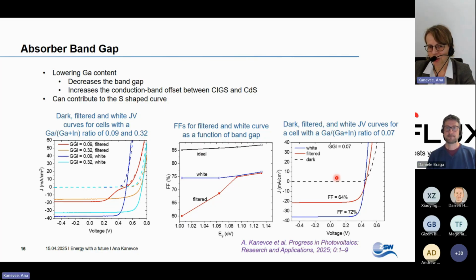So in a single junction, this is why we encounter those problems, because if you optimize a cell for a single junction, it's completely relevant to say, I need to expose my cell for a couple of seconds to white light and it's working wonderfully. So I don't think that this is... There was quite a bit of research on this S-shaped curve some years ago, but this was mainly from academic curiosity, because we wanted to understand what is going on with the buffers, what is going on with metastabilities and with the defects. But now this is not just a scientific curiosity. Now the cells will not work if we don't look at these features. So we have to really address these problems.